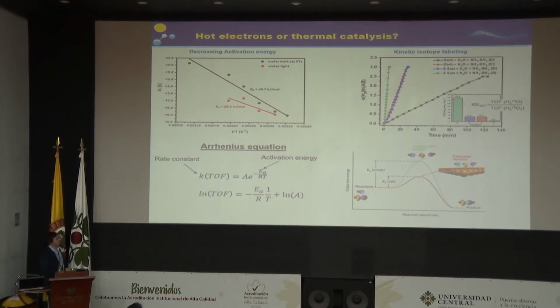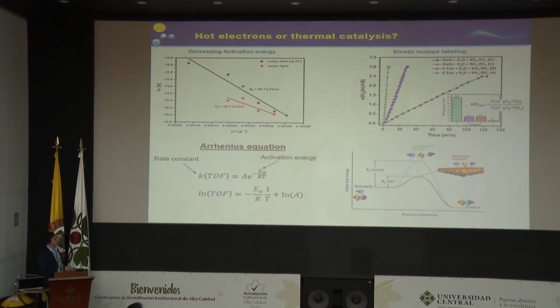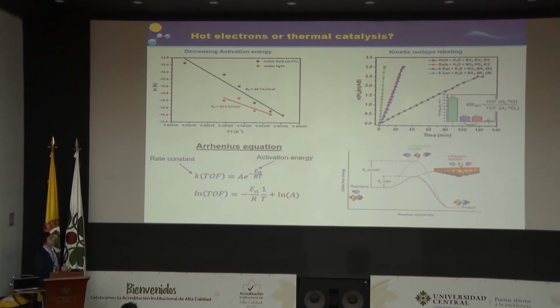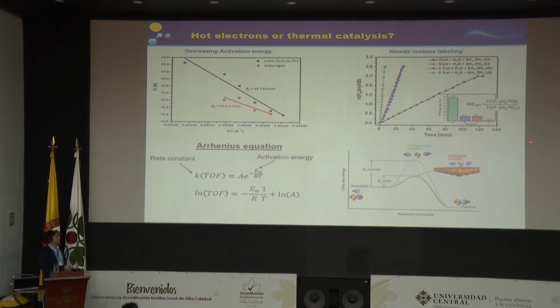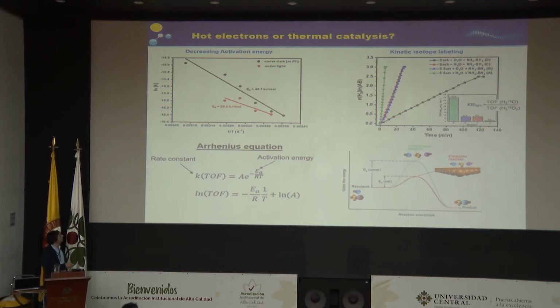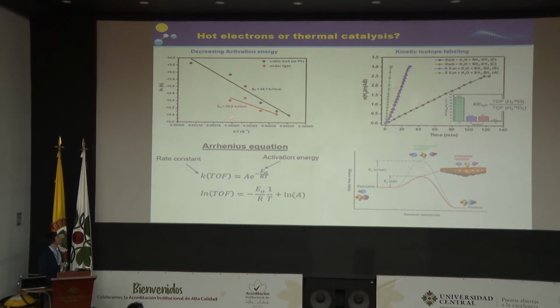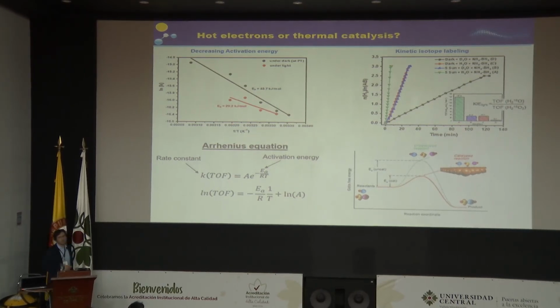So this is a normal thermal reaction, and this is a catalyzed reaction. We decrease the activation energy barrier of the reaction by using hot electrons, and specifically, using an Arrhenius equation, we see that we can decrease by 20 kilojoules per mole the energy needed to drive the reaction, if we compare the photochemical to the thermal reaction itself.